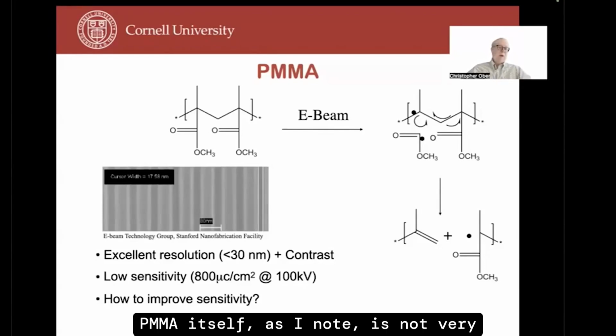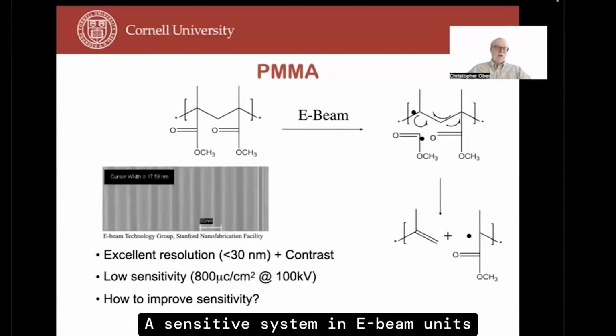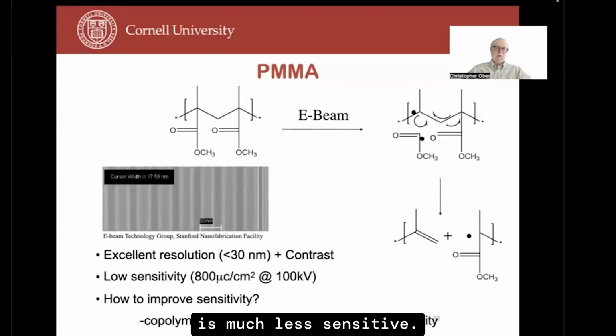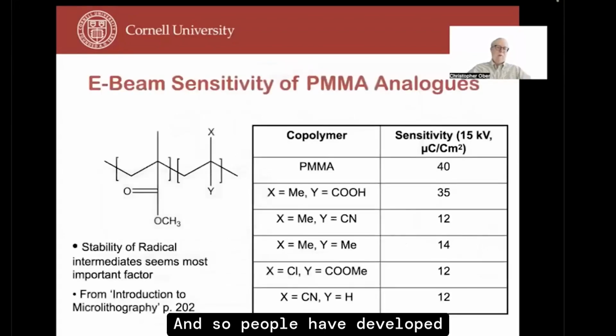PMMA itself, as I note, is not very sensitive. A sensitive system in e-beam units would be 10 microcoulombs per centimeter squared, roughly. So 800 is much less sensitive. And so people have developed variations of PMMA.